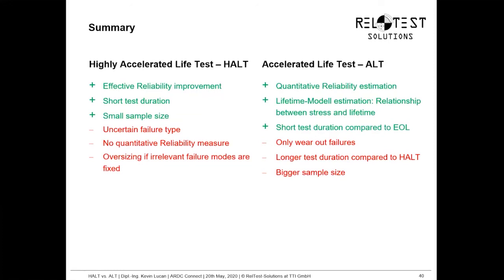Another disadvantage is we only want to see wear-out failures in an accelerated life test. So in most of the cases, when we're doing an accelerated life test, we still have to deal with early failures. It's quite probable that we have to redo our accelerated life test after we have fixed these early failures. Of course, estimating a lifetime model is connected with a little bit of effort, so we have a quite big sample size in accelerated life tests.